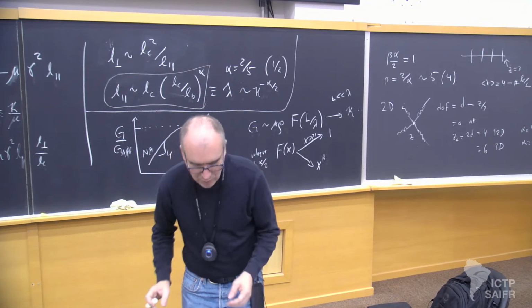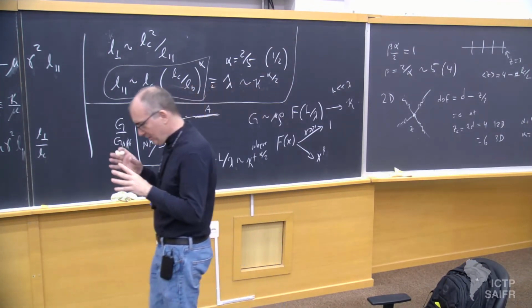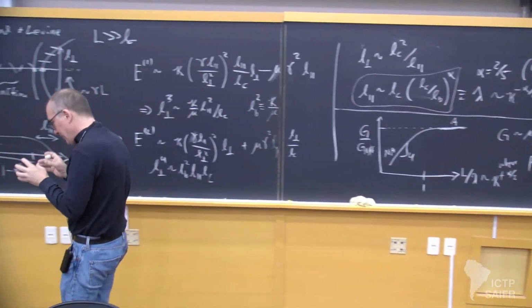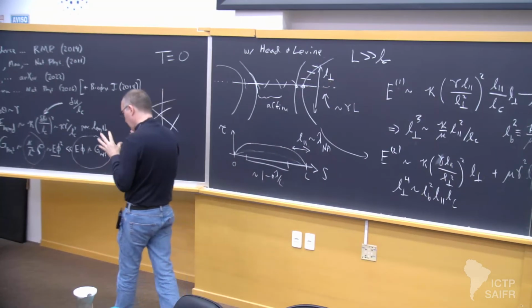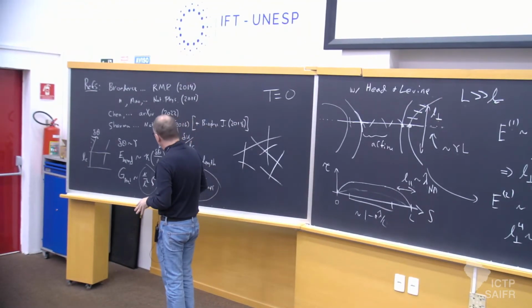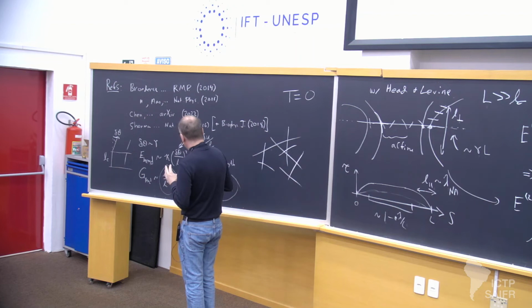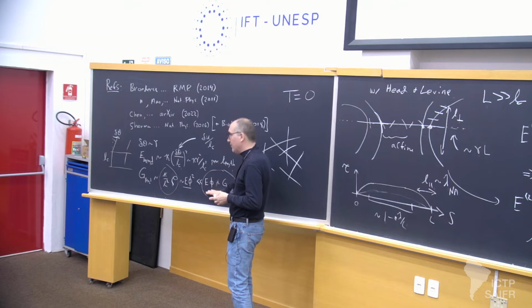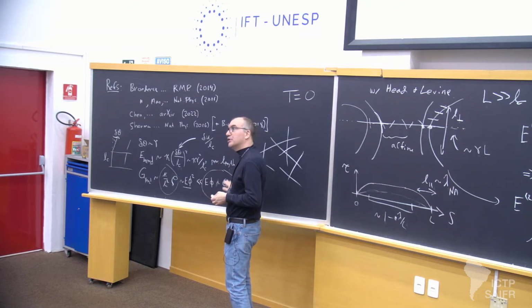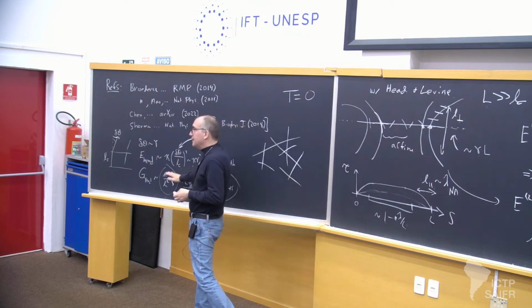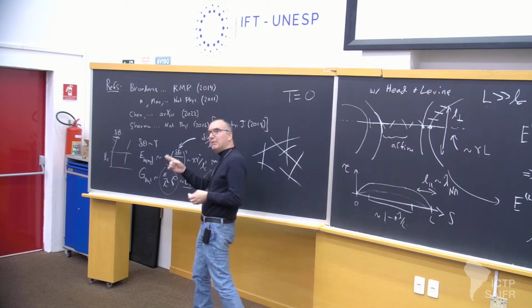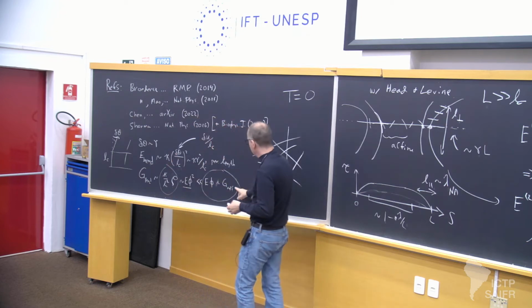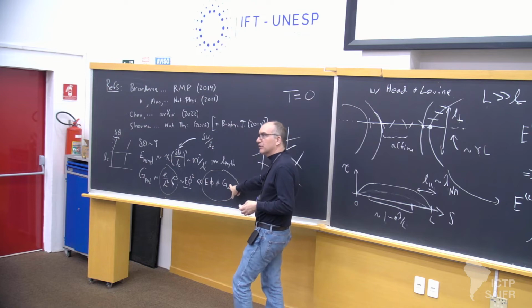Okay, so I would say we now have 3 distinct network regimes. We have the possibility, even in an athermal system, provided the molecular weight's high enough, to achieve this high value of modulus. You can also get typically a lower value if you go to smaller molecular weights. And we have that thermal mechanism I mentioned before, which basically takes this and softens it by thermal fluctuations.